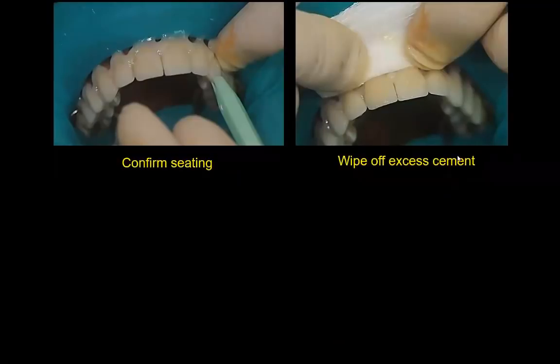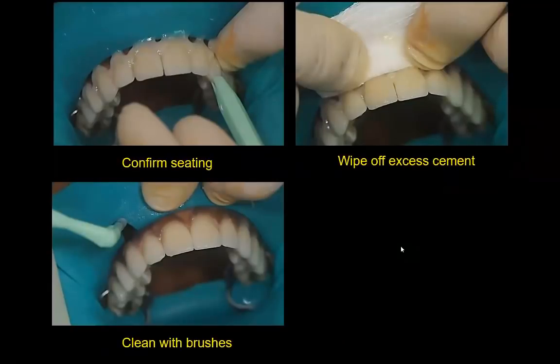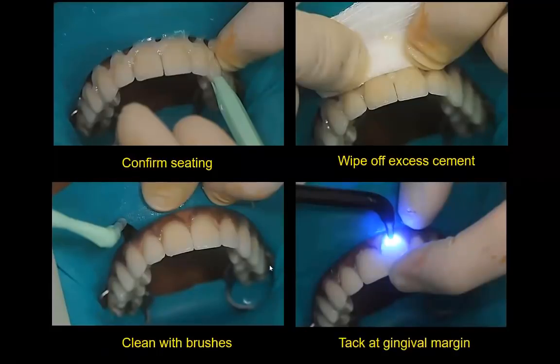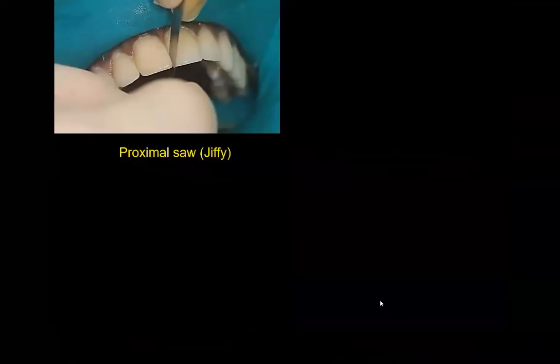Then we take cotton rolls. First off, we make sure everything is seated once all 10 are in. Then we take gauze and cotton rolls, brushes. We wipe away all the excess, everything facial and lingual. There's no excess on these teeth except interproximally. And I can't floss if they're moving around. So I hold my finger on here so it doesn't move. I hold light pressure in a lingual direction here. And then I tack with a very small tacking tip for about 3 to 5 seconds. Go through all 10 teeth.